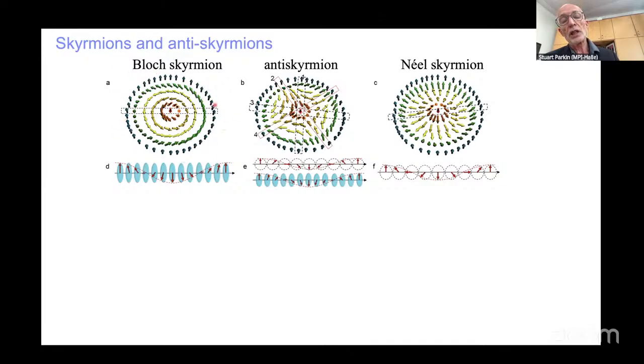In this case, this Bloch wall here, you can see the magnetization rotates from an up direction on the outside to a down direction on the inside, and it rotates in a plane which is parallel to the tangent to this object. And all the way around the object, the magnetization rotates in the same way. So on the right-hand side, you see the magnetization in the middle of the domain wall is pointing up. On the left-hand side, it is pointing down, because the chirality is the same all around this object, and the chirality is typically introduced by a bulk version of this exchange interaction, this Dzyaloshinskii-Moriya exchange. So it's typically found in systems with a lot of spin-orbit coupling.